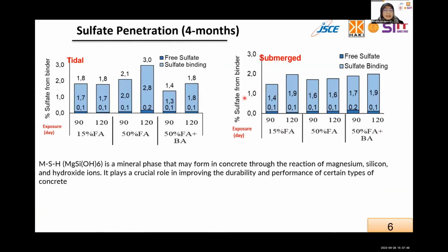And here is the sulfate penetrations. Sulfate does exist in the concrete at the depth of 5 centimeters after 4 months immersion in the seawater. And the tidal area shows very much sulfate to contaminate and decompose calcium silicate hydrate in concrete. Then we know that exposure to the seawater sulfates, the water contains sulfate ions, which can infiltrate the concrete structures. When the sulfate ions come in contact with the concrete, they can react with the calcium aluminate compounds in the cementitious matrix. The formation of the here MSH is a complex chemical process that may occur over time as the concrete matures and cures.